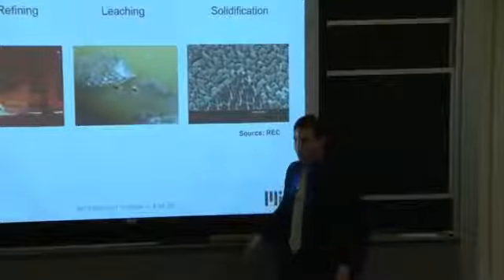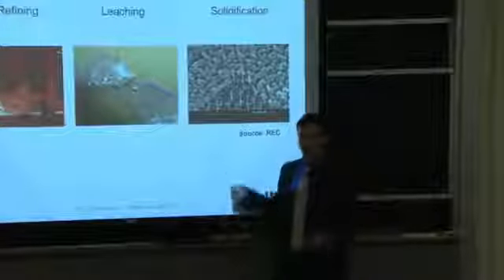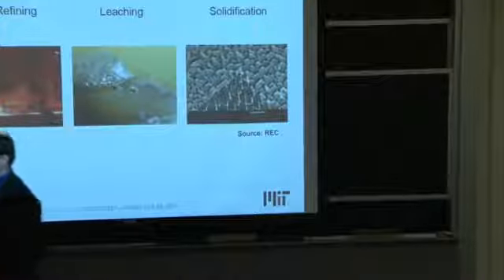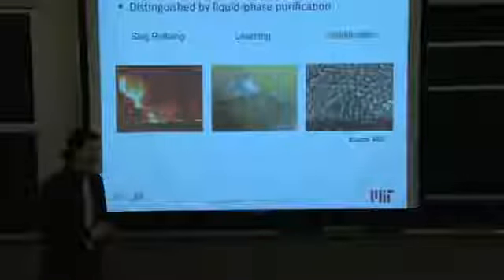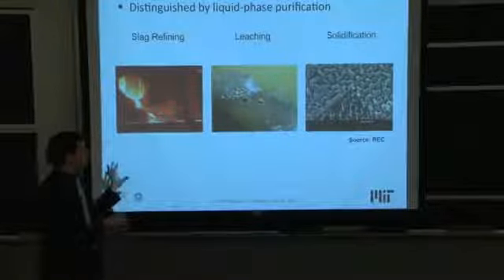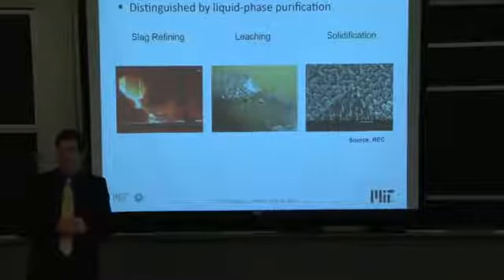So the solidification process doesn't come without a yield penalty. You still throw away some of your material. So you can't repeat the solidification over and over and over again. I guess you could, but you'd be losing material every step. So some combination of these processes here and others, other trickery, low temperature eutectic formation with other elements, for example, some combination of this is used to refine the silicon without creating a gas out of it.